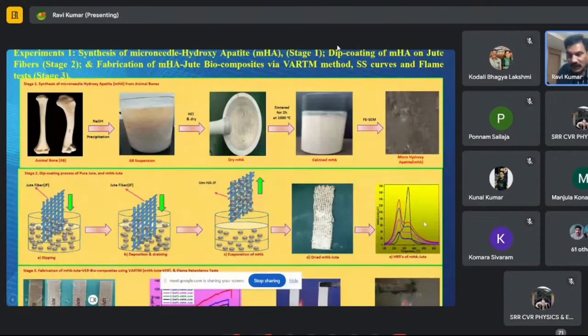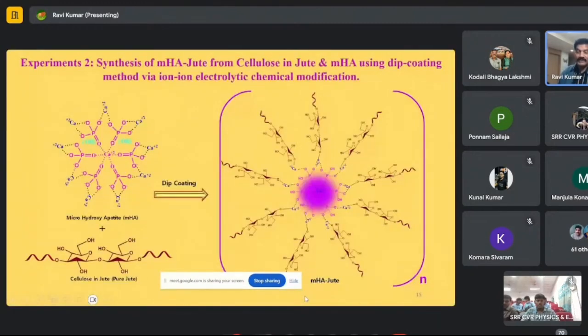So here I will explain in the next slide, because this is only the overview of the material. And also I told you we made pure jute panels with vinyl ester resin before and after deposition of flame retardant material, and also we checked the surface and quantities and flame retardant technology here. And here, how we make the synthesis of MHA jute from cellulose in jute and MHA using the dip coating method via ion-ion electrolytic chemical modification.